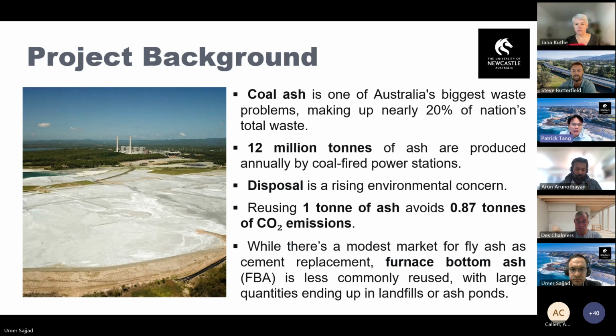And at the moment, each year, around 12 million tons of ash are produced by coal-fired power stations. Disposal of this ash is becoming an increasing environmental concern. But the good news is that by reusing 1 ton of ash, we can prevent approximately 0.87 tons of CO2 emissions. While there is a modest market for fly ash as cement replacement, furnace bottom ash is relatively less commonly used, and large quantities of FBA end up in landfills or ash ponds.